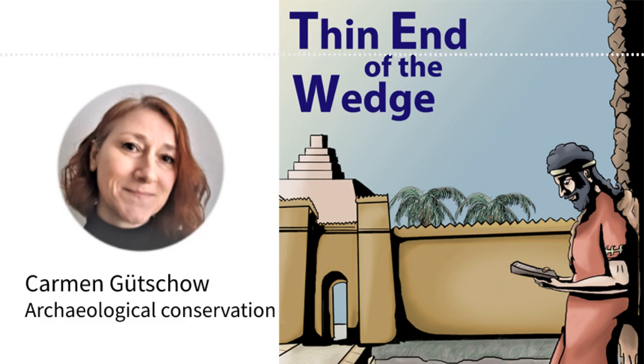Once the pottery fragments — or sherds as they're called — are cleaned, sometimes it's possible to join them back together into a more or less complete pot. To join the pottery is a bit like a 3D puzzle. Most people think the bonding is easy, but if you have seen some objects joined by a layperson, you will see it's not that easy, and it's time consuming to rework. To make a proper bond, you have to follow some rules. For example, a weak breakage will need a consolidation before, and a more rough shard needs a thicker glue than a finer one. If you don't have a full contact area, you will need a filler in your glue. And don't smear the surplus over the surface — remove it directly — or if you have bubbles or run marks, for example.